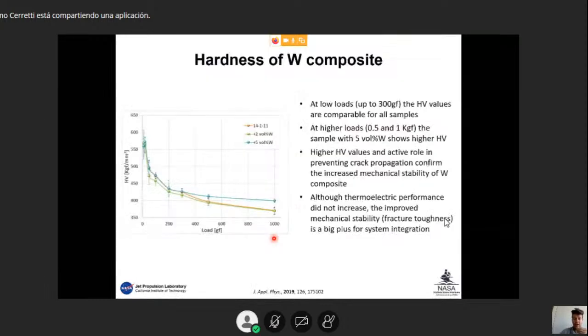mechanically resistant. And indeed, when we then plot the values of the hardness, we saw that at higher loads there's an increase for the 5 volume percent, and that was a proof of the better stiffness of the material. So although the thermoelectric performance did not increase, improved mechanical stability and fracture toughness especially is a very big plus for the integration into the generator.